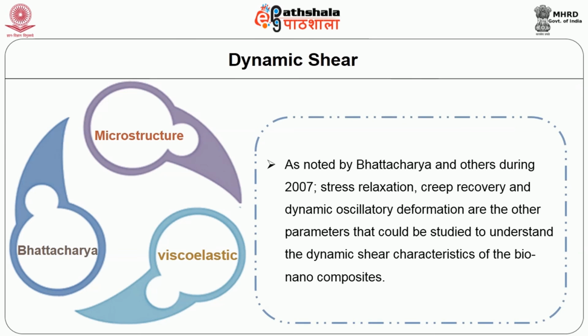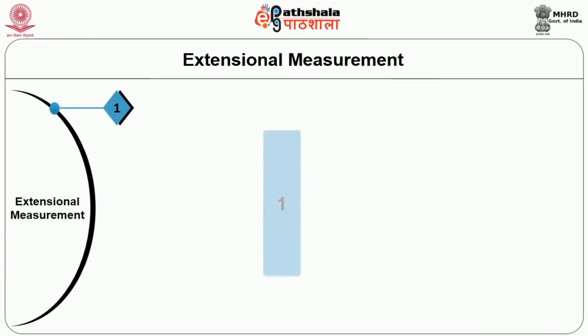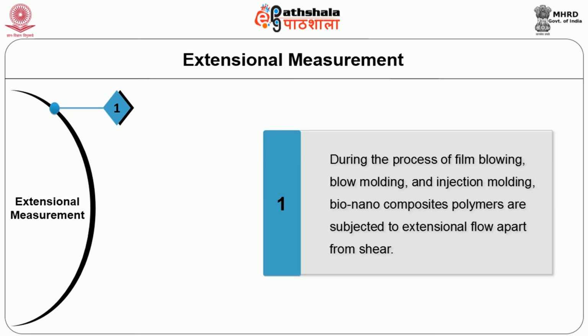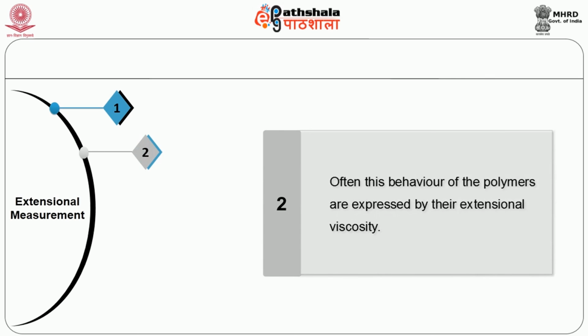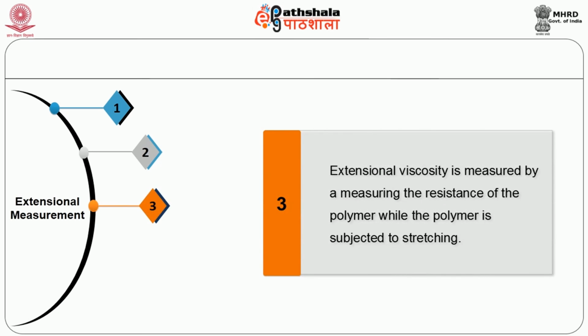As noted by Bhattacharya and others in 2007, stress relaxation, creep recovery, and dynamic oscillatory deformation are the other parameters that could be studied to understand the dynamic shear characteristics of bio-nanocomposites. Finally, it is the extensional measurements. During the process of film blowing, blow molding, and injection molding, bio-nanocomposite polymers are subjected to extensional flow apart from shear flow. Often, this behavior of the polymers is expressed by their extensional viscosity. Extensional viscosity is measured by measuring the resistance of the polymer while the polymer is subjected to stretching.